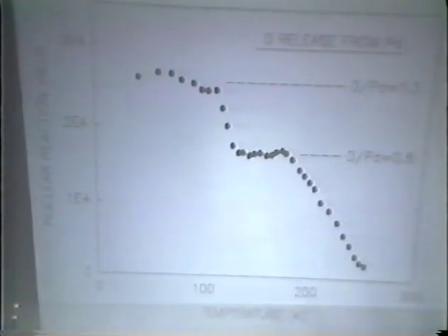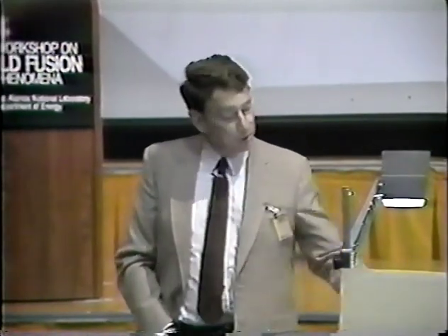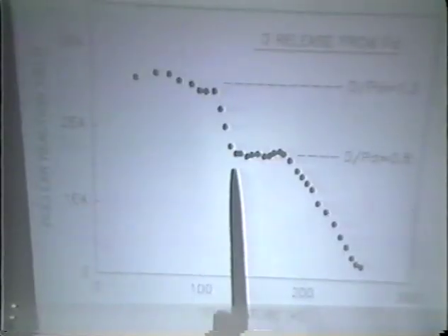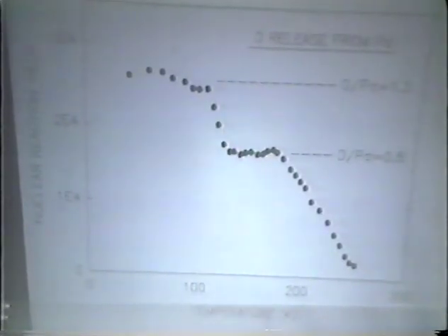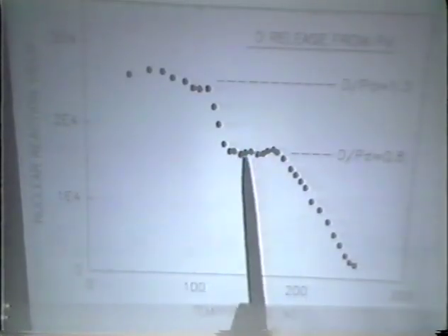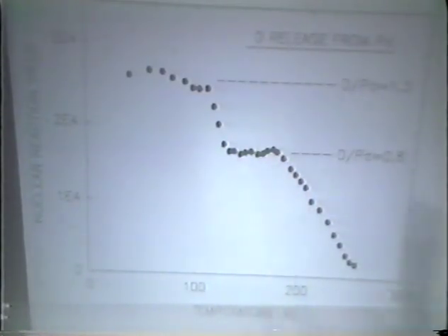However, totally unexpected for compositions below 1 is this rather sharp and well-defined stage down at about 120 Kelvin. I think that suggests an obvious interpretation, that we're losing the superstoichiometry in this stage, and in fact you see that we do pop down to a composition more or less conforming to those that we have heard discussed so much this week. Why would the excess diffuse more rapidly?